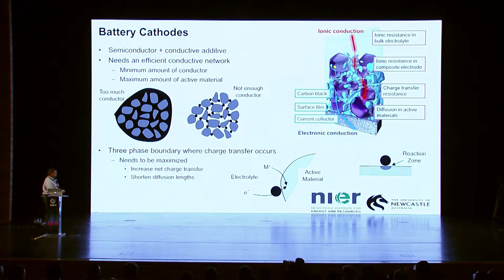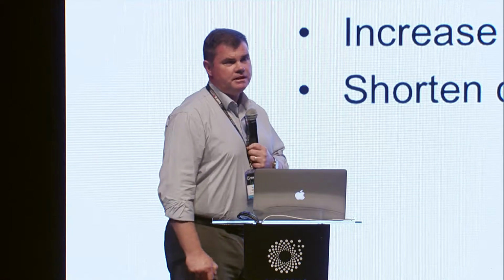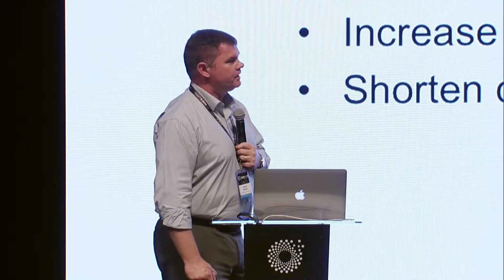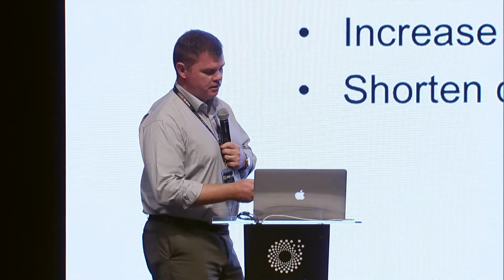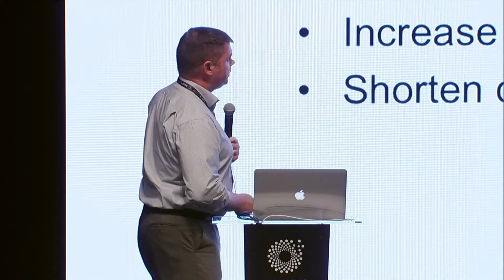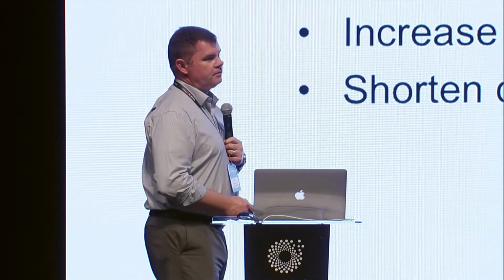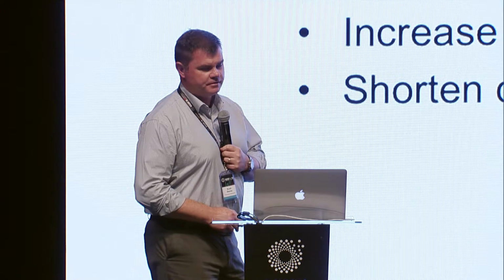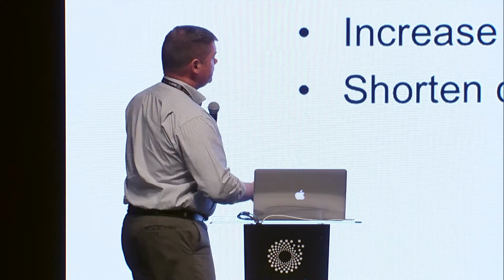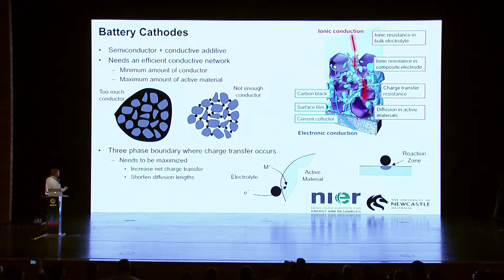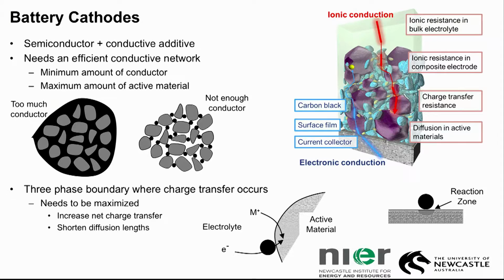Right, and so what it means then is that it becomes a balance. There's a need to have a balance between the active material in the cathode and also the conducting material in the cathode. And so that's where we need to optimize the relative amount of conductive element within that system. Right, and so you can see here on the left where you can have too much conductor, not enough conductor, and that will limit your performance.